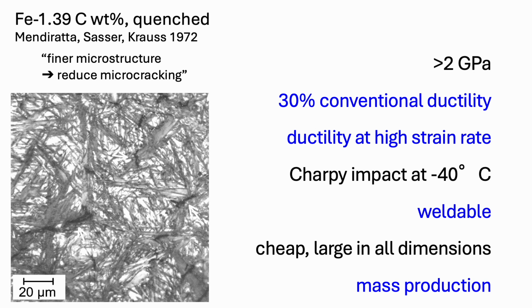So this is like a dream scenario, that we do no heat treatment after producing the martensite, and yet, you know, we have a large amount of ductility, toughness at minus 40 degrees centigrade, and so on. So this is not a dream. In fact, we have done this, and even written it up in my book.